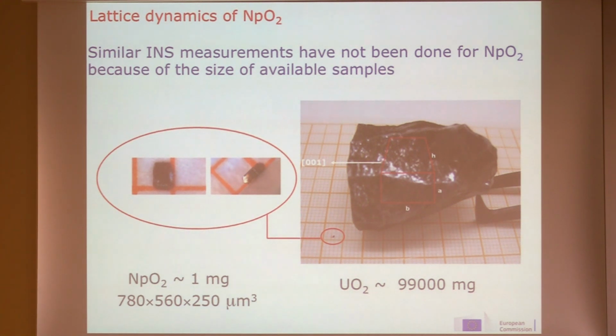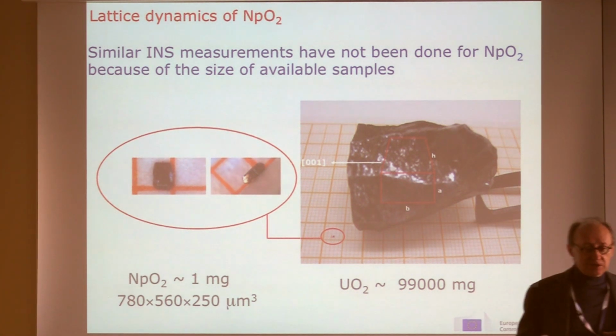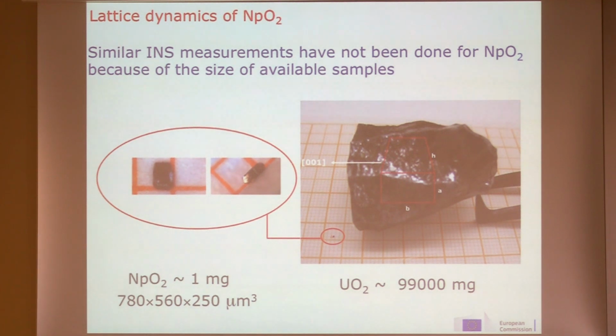You can do elastic diffraction. We did polarized neutron diffraction studies and crystallographic studies and measurements of diffuse scattering, but still, even for diffraction, it is very demanding, also because neptunium has a strong absorption cross-section with a resonance at about 270 milli-electron-volt that produces, even at the milli-electron-volt range, a very strong absorption.